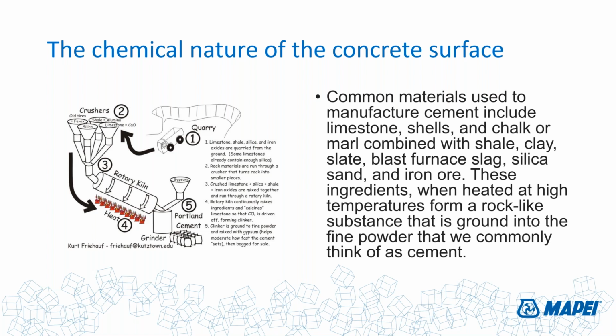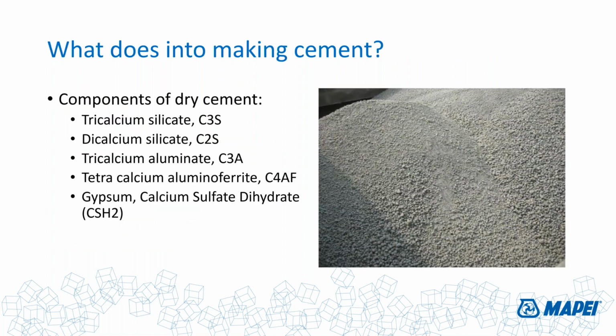Let's take a little bit of discussion about what goes into making concrete. And for those of you who are on the phone, I'm sure many of you know quite a bit about this, maybe more than me, which is entirely possible. But just be aware that concrete is made out of cement to start with. Where does cement come from? It's from limestone, chalk, basically calcium carbonate combined with shale, which is the aluminum and the silicate part of it, with iron and silica sand and so on and so forth. All these things are put into a rotary kiln, turned and taken up to an incredible amount of heat, over 2,000 degrees Fahrenheit. And you create a thing called clinker. The clinker goes to the grinder, and that creates what we commonly know as Portland cement. So it's a very interesting, complicated chemical process, and creates a very hygroscopic material in the form of cement. It wants to go back into a more common state. So this is what comes out of that when the process is all done.